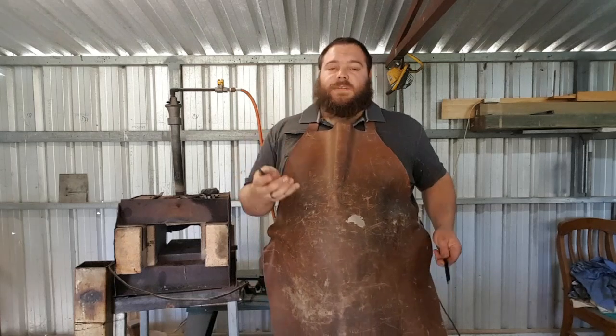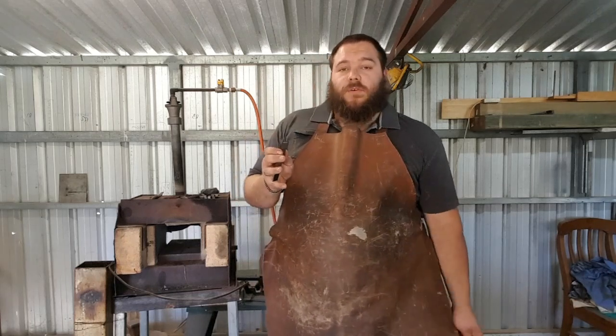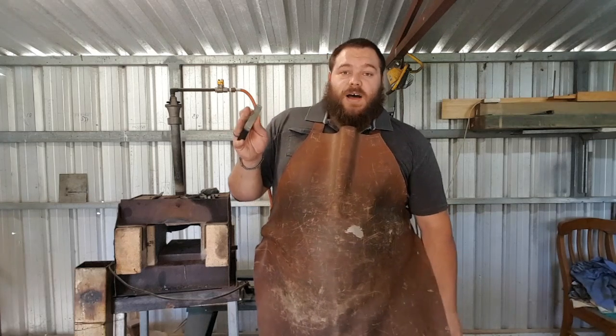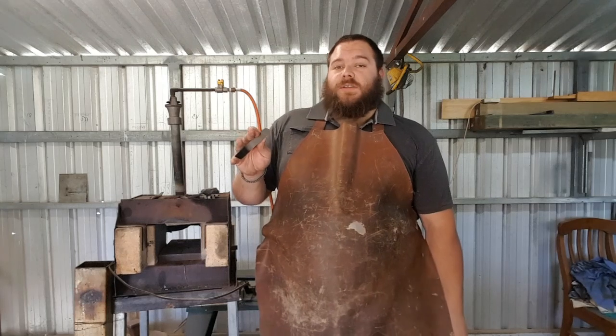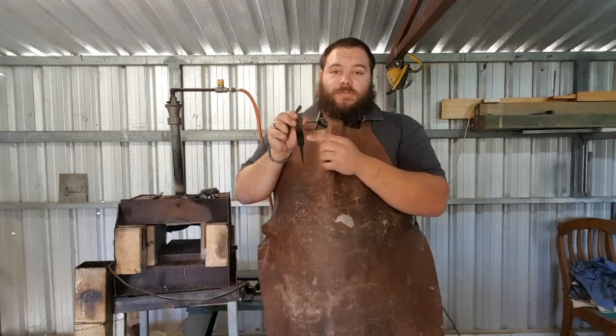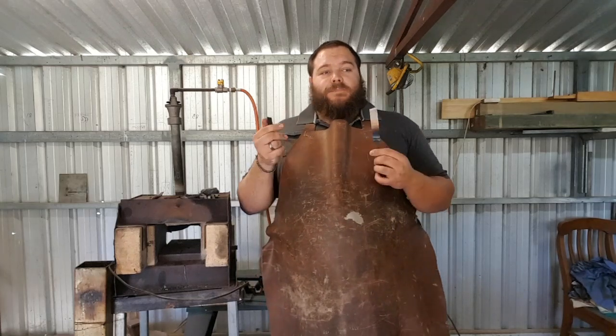And that means that you can have a false reading. Now, I get that with oven tempers sometimes. If I've cleaned a piece of material before I temper it in the oven, if you leave it in there for 4.5 hours or 5 hours at 180 degrees, although the temperature has not changed, you may have a blue blade when you pull it out. It may look that color, blue. And the problem is that could tell you, oh my god, I've over-tempered it, it's way too soft.